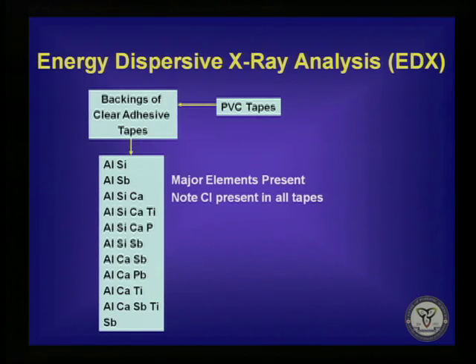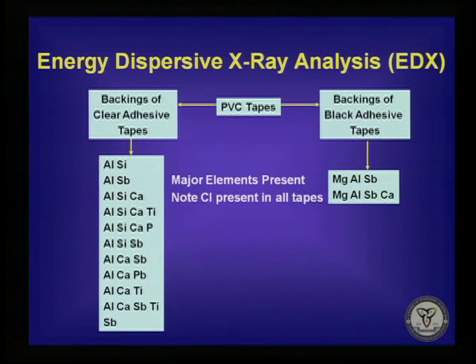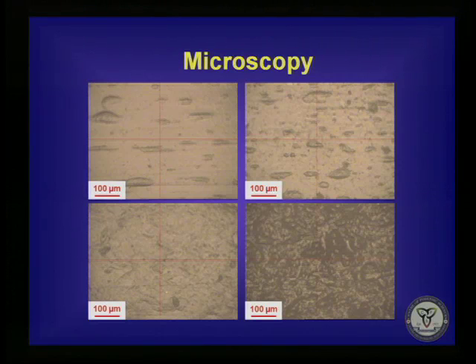Energy dispersive X-ray analysis. For the clear-backed tapes, we had a combination of different elements present in these tapes, and this data is just for the backings, but we did look at EDX of the adhesives as well. And I just listed the main elements present. Some of the minor ones are not listed here, so you can see there's a lot of variability. And the backings of the black adhesives had less variability in the elements present. These are photomicrographs taken through a video camera on the laser ablation ICP-MS, and you can see the features of the backings and how they vary. So the top two tapes have calendaring marks, and the bottom two tapes have different amounts of surface roughness.